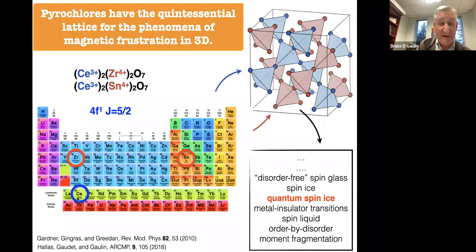And so cerium is here. It's at the beginning of the rare earth series, right? So cerium 3+ has a 4f1 configuration, and if you use Hund's rule to calculate what the total angular momentum is for 4f1, it turns out it's J = 5/2. So it's right at the opening of the 4f series.